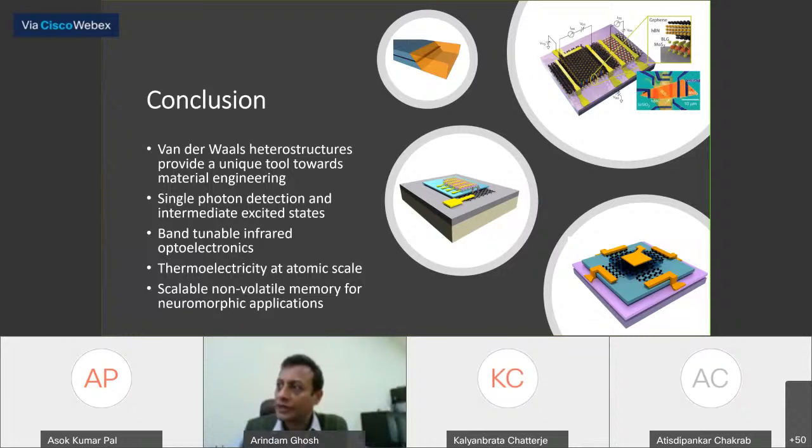For example, when graphene first came in 2004, 2005, a lot of fundamental issues came out: can a purely two-dimensional structure be structurally stable? Normally there is even a theorem called the Mermin-Wagner theorem, which says that such structures are intrinsically unstable. But it turns out that the interaction with the substrate can probably make such structures stable. But not all of them.